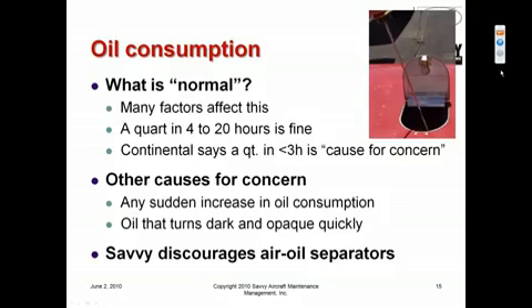One other comment regarding oil consumption. A lot of owners who have high oil consumption will try to reduce the oil consumption by adding an aftermarket air-oil separator. We strongly recommend against doing that. It's not only a band-aid that is curing the symptom rather than curing the underlying problem, but there are a couple of very bad things about air-oil separators. One is that it's hiding a very important symptom. If an engine has a pressurized crankcase and therefore is losing a lot of oil out the breather, we want to know about that and fix it. And if you put an air-oil separator on the engine to make the symptom go away, then it can cover up a serious internal problem with the engine. We don't want to cover it up. We want to find it and fix it.